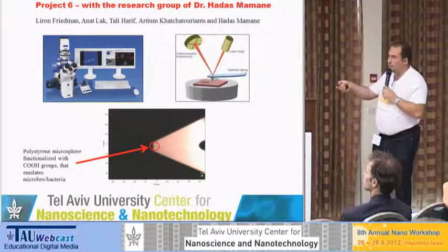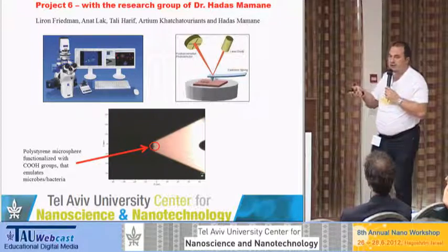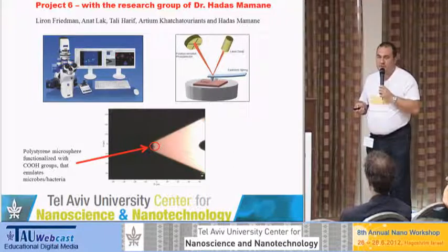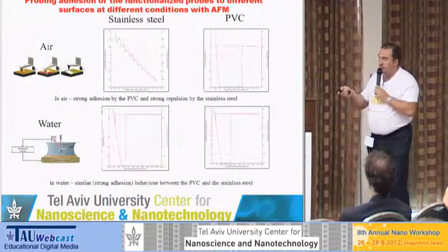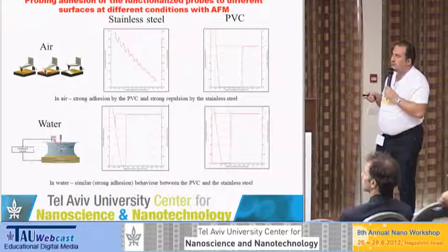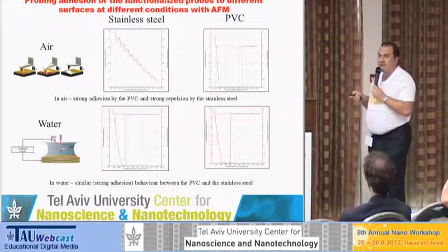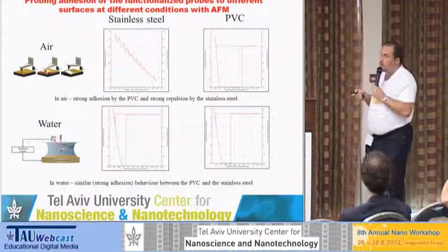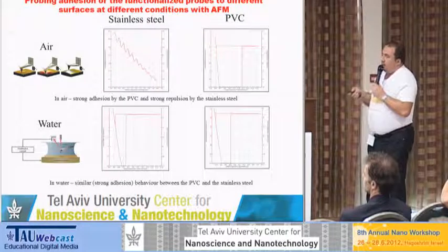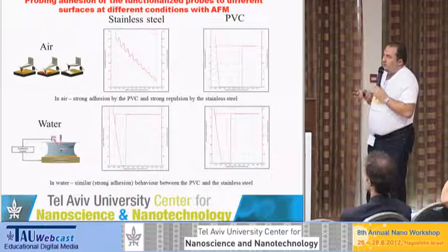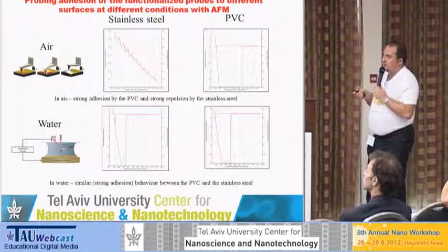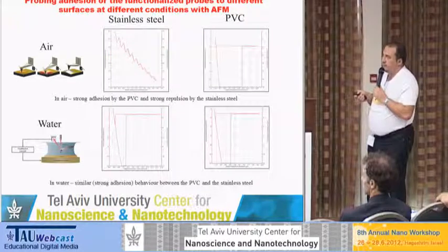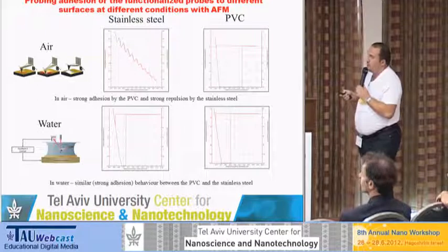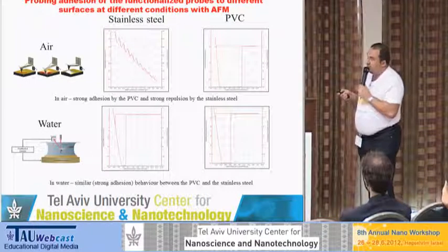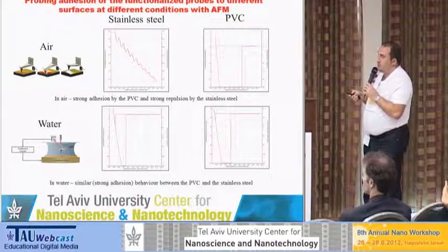For these purposes, we use a functionalized AFM probe, where you can see a 1 micron sized polystyrene bead functionalized with carboxyl groups, and this emulates the presence of microbacteria. And then we try different surfaces, different materials in air and in water, and see the adhesion of this probe to them by acquiring force distance curves. Here, for example, in air, you can see that for stainless steel, the force distance curve is very unusual. It indicates strong repulsion and even oscillation of the tip, while for PVC, it is also unusual. Not like a regular AFM tip, regular sample. Here there is a strong adhesion.